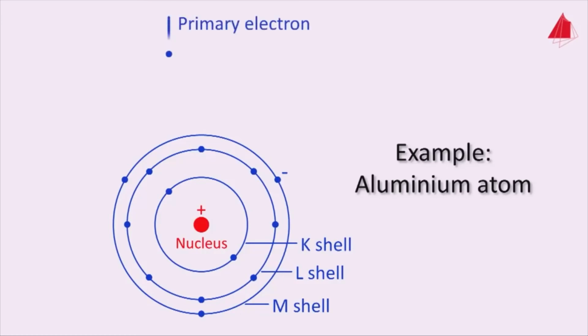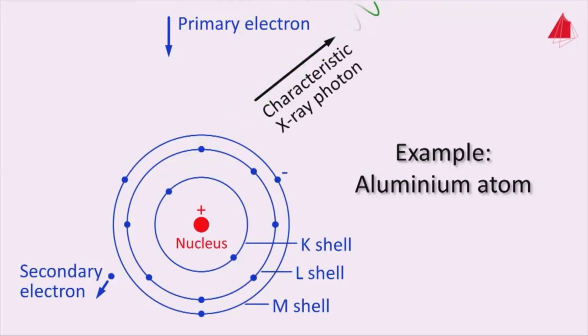A primary electron comes from above and accidentally knocks out an electron from the K-shell of the sample atom. A vacant place remains as indicated by the yellow circle. This state is unstable. An electron from the L-shell fills the gap and the energy difference is released in the form of a characteristic X-ray photon. This X-ray photon is called characteristic because its energy is quite characteristic or typical for the particular element. Now another transition follows, and finally the atom repairs itself with an electron from the vicinity, a free electron.